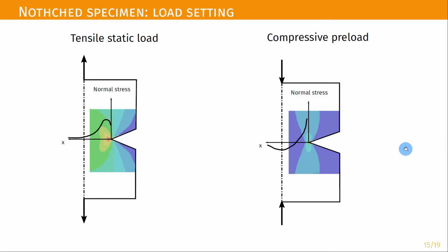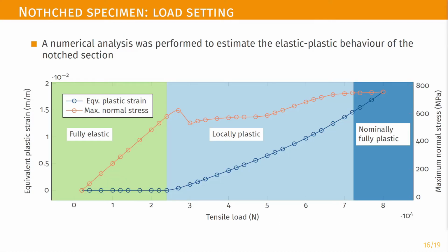So the idea is to follow two different ways for doing the experimental test. In the first one, the test will be performed with a fixed preload that will be maintained during the fatigue test, while in the second one, the notch specimen will be compressed to locally go beyond the yield strength of the material in order to create residual tensile stresses in the region of the notch. In a similar way as for the welded joints, the aim here is to reproduce locally the stress state that is comparable to that produced in the weld seam, hence the choice of the notch specimen.